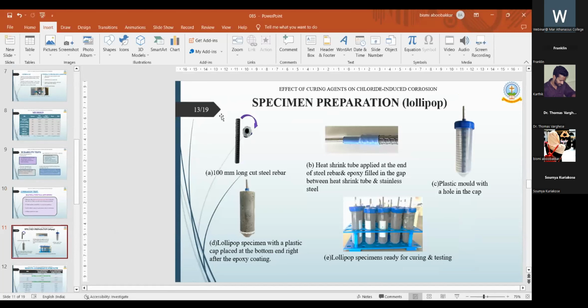This is how the specimen is prepared. First, a long steel bar is cut, then heat shrink tube is applied at the end of the steel bar, then it is placed in the plastic mold, and then the mortar is placed. Then after 24 hours, epoxy is applied at the top and bottom of the specimen. Then after drying, the specimen is ready for curing and testing.